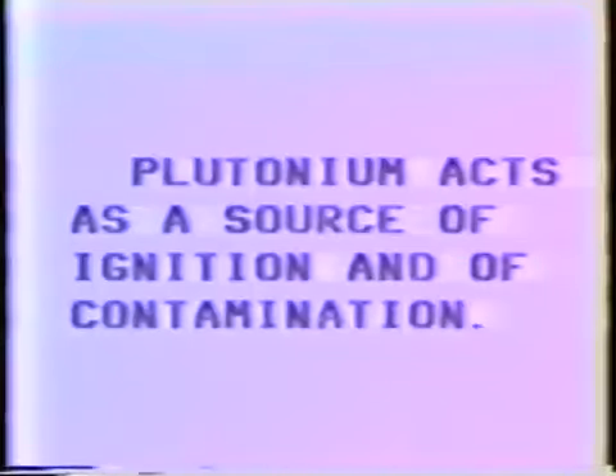So the principal concern in a glove box fire involving plutonium is to prevent the ignition of other materials such as plastic, paper, wood, anything else that will burn. And so the concern is not to put out the plutonium metal fire, because the plutonium is going to have to be recycled for cleanup anyway. The main thing is to prevent it from igniting some other source. So if you keep this in mind, this is the real message that comes out of these plutonium metal fire tests.